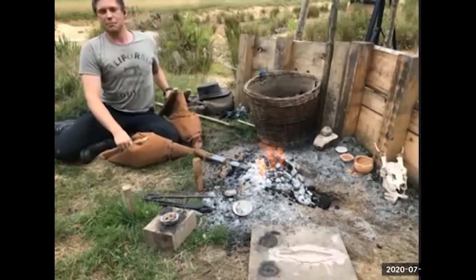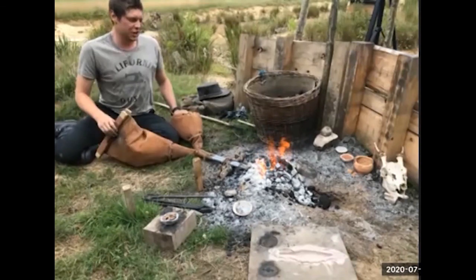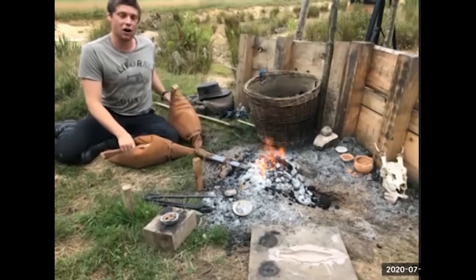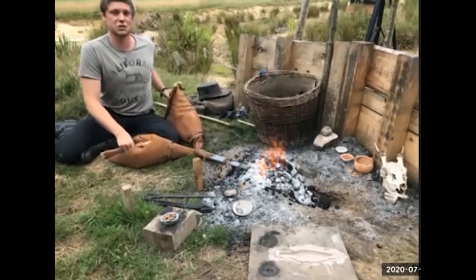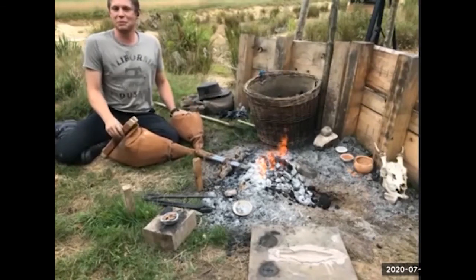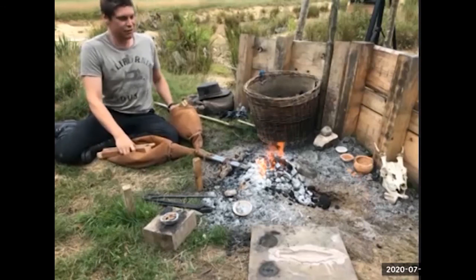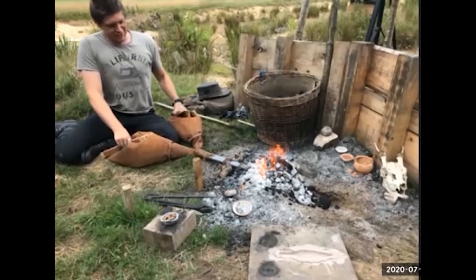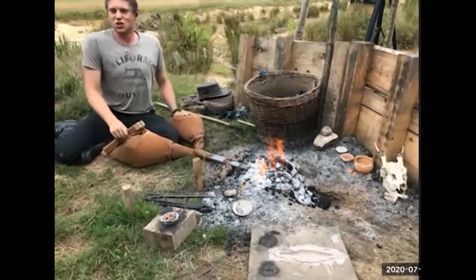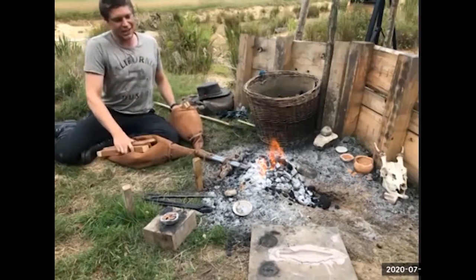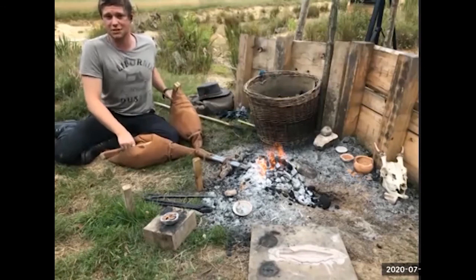ideally we've got to get the copper to melt around about 1,150 degrees. That's really hot. And the ceramic which holds it, the crucible, starts to dissolve around about 1,000 degrees. So we have to very rapidly, but in a controlled manner, heat it up, melt the copper, which then mixes with the tin.